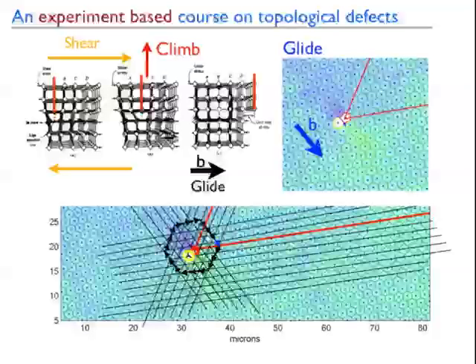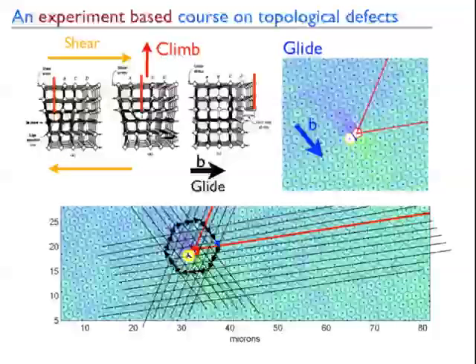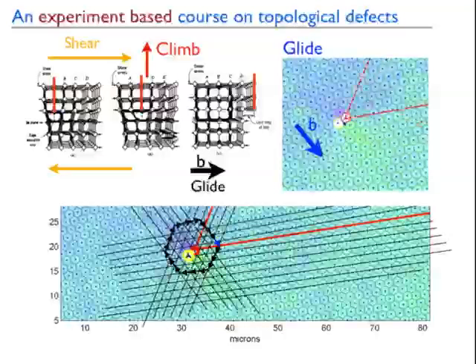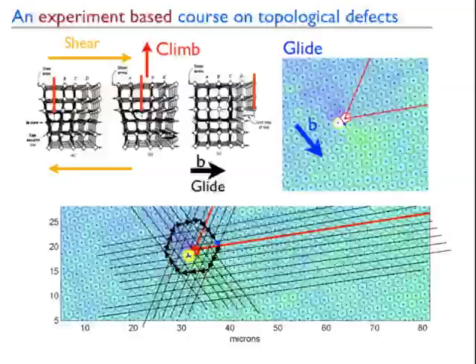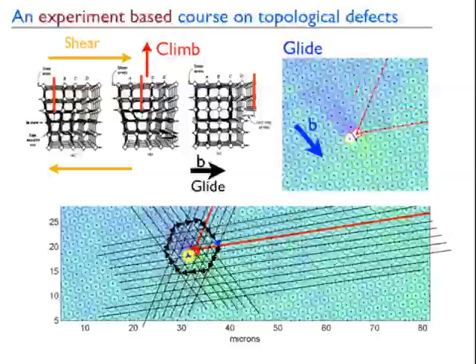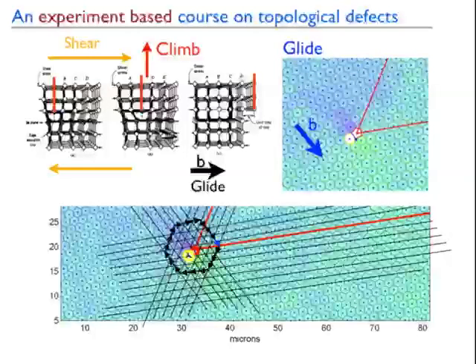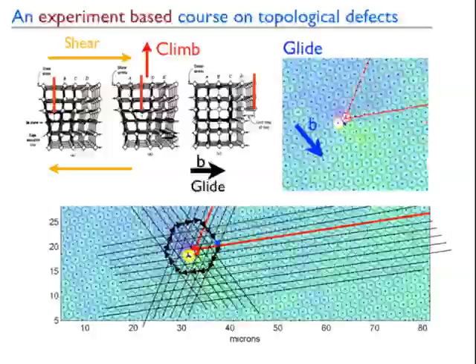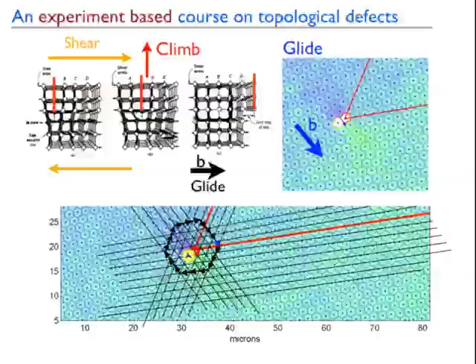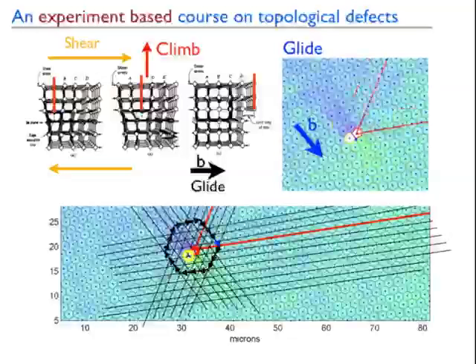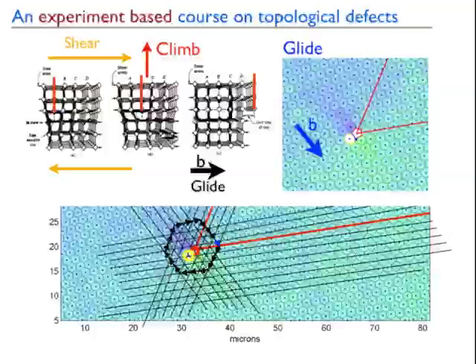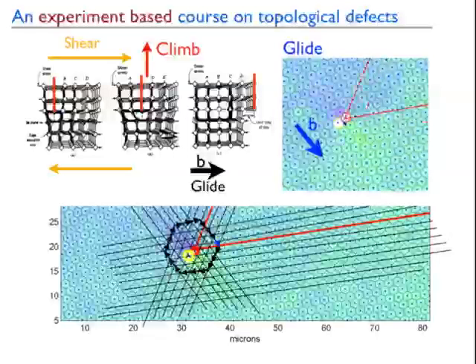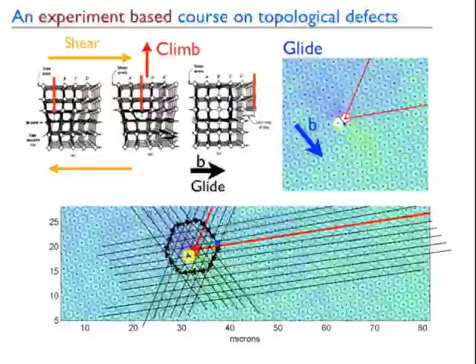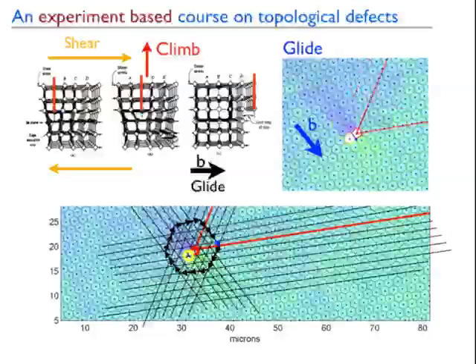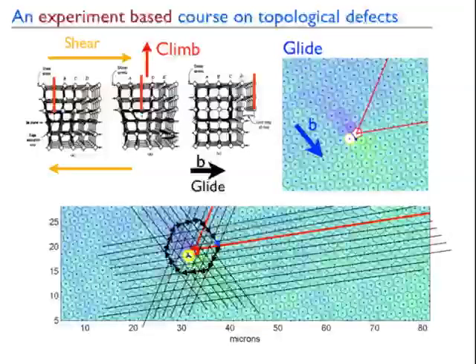They give you rigidity. And two-dimensional melting is completely about whether these dislocations are bound or not. The same thing happens for superconductors. In superconductors, what plays the role of the dislocations are vortices. If the vortices are unpinned, you're not superconducting. That is, you get a resistance. If they're pinned, then it's rigid, and you get a superconductor, and the phase is locked. Here is a dislocation that is simply undergoing thermal gliding over here.